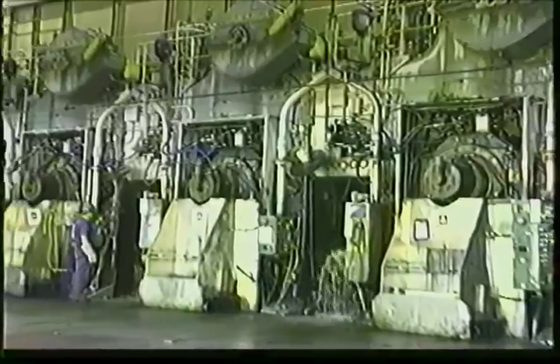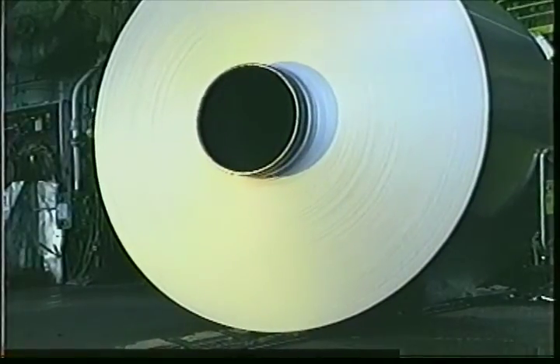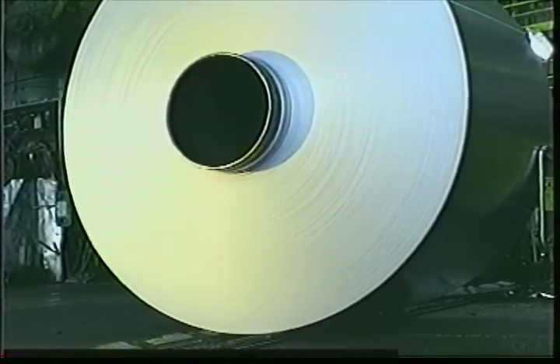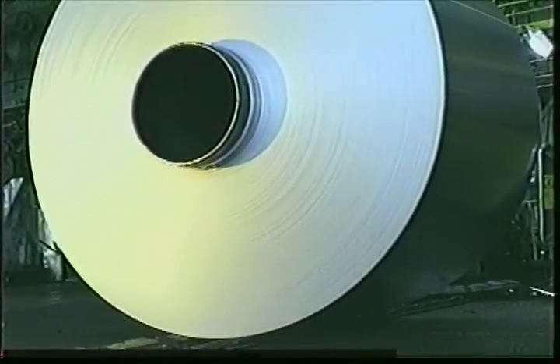At the cold mills, the metal moves through each step at an extremely high speed, 5,000 feet per minute to be exact. The two multi-stand cold mills will take the metal to its final gauge. Entering the mill at its original thickness of 1/8 of an inch, it exits the final reduction in a coil of aluminum 7 miles long and 8/1000ths of an inch thick.